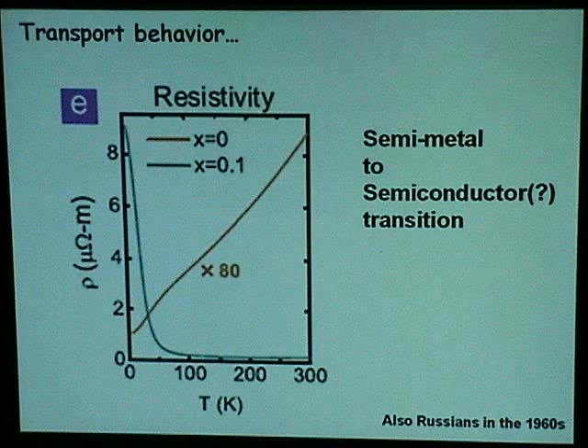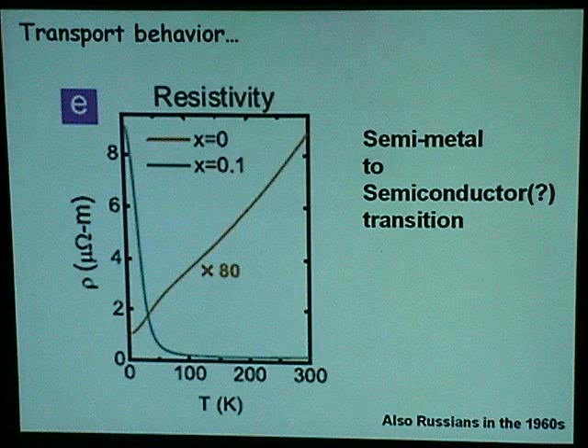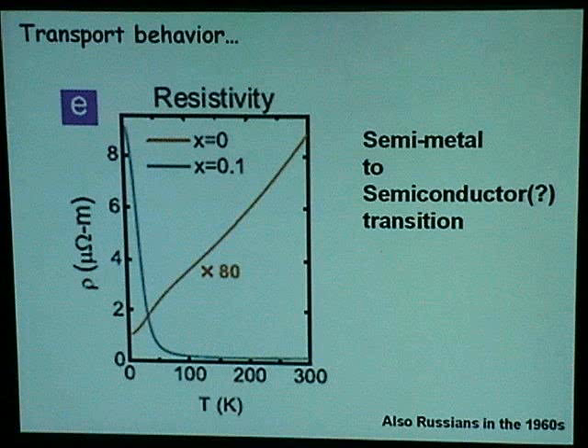So what we see is that if you dope it with antimony or tin, then you get a very large resistivity into the semiconducting regime, and it does have a gap, as I will show. If you look into this Russian literature, they could never resolve whether the saturation is due to imperfections or it is an intrinsic effect, because nobody has ever found a pure insulating state in bismuth-based compounds. And I'm jumping a bit, but I think it has to do with some metallic surface state, which is topologically protected, which always contributes to conductivity.